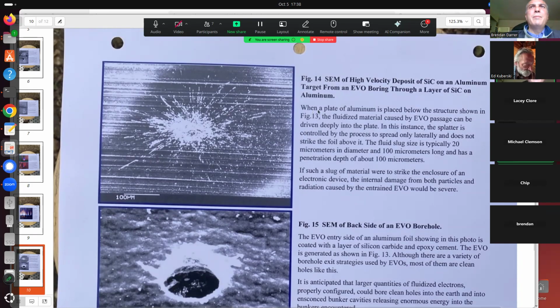When a plate of aluminium is placed below the structure shown in figure 13, the fluidized material caused by the EVO passage can be driven deeply into the plate. In this instance, the splatter is controlled by the process to spread only laterally and does not strike the foil above it. The fluid slug size is typically 20 micrometers in diameter and 100 micrometers long, and has a penetration depth of about 100 micrometers. If such a slug of material were to strike the enclosure of an electronic device, the internal damage from both particles and radiation caused by the entrained EVO would be severe.